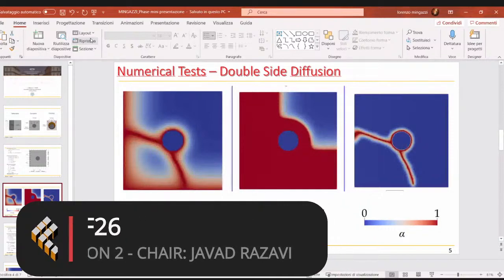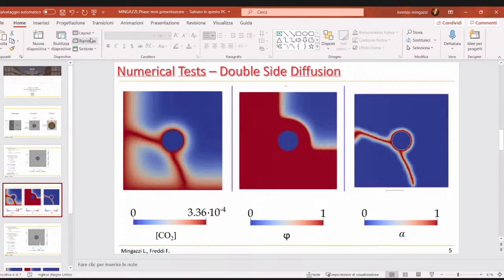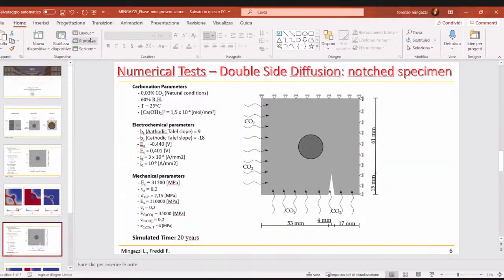As we can see, the carbonation profiles respect the environmental condition we set for the numerical test, and we can see that the phase field approach to brittle fracture is capable to correctly describe the effects of the different environmental condition affecting our specimen. As we can see, the cracks nucleate and evolve towards the sites from which the carbon dioxide enters the specimen. The second test we perform, we took the same domain.